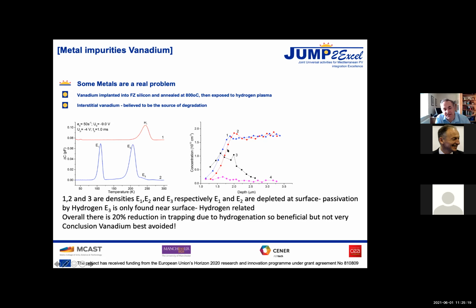So we do that in this case, and we find that the trap decreases. So that suggests that hydrogen is passivating them. Because we introduce hydrogen at the surface, it passivates most of them, but it doesn't seem to passivate number 3. And this is a small amount of vanadium, and also the hydrogen isn't very effective compared to most metals.